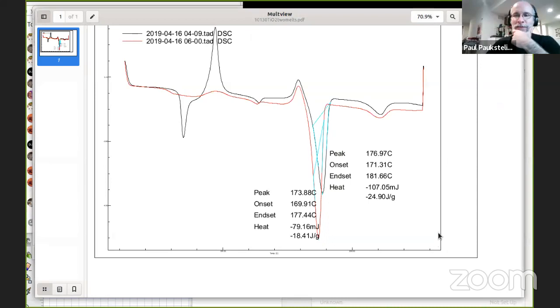And without a doubt, the white filaments with titanium dioxide have very, very strange melting. I mean, there's little peaks and valleys and bumps all along where you would normally expect it to be just a smooth curve. Yep. I actually, just as we were talking, I pulled it up. I'll try and share this.